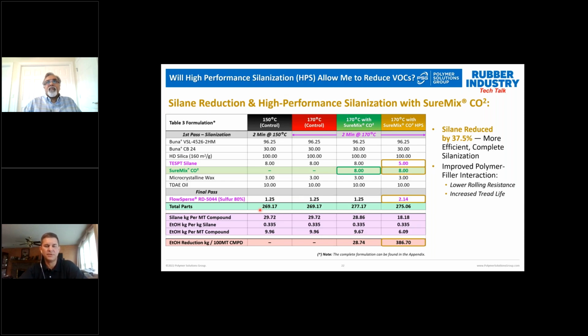So this is what we call high performance silanization, and let me give you a little bit of background before I jump into the data. When you think about use of silane in a silica compound, in a silica tread, the majority of the work that was done to establish silane loadings was done obviously many years ago, and was done using Si69 type silane, so tetrasulfide type silane, and it was done within the bounds of processability.